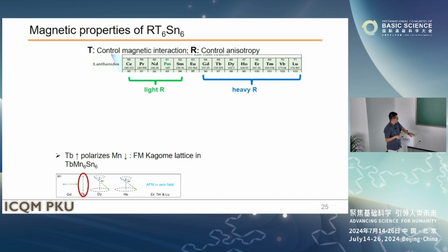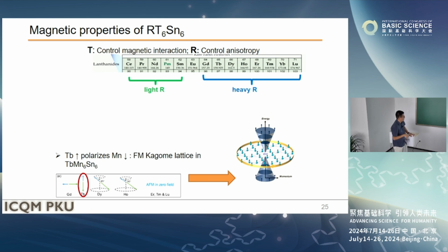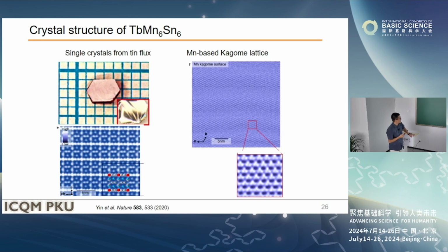And because the rare earth moment is highly localized and has strong anisotropy, depending on the crystal electric field effect, you can expect many different anisotropies for these compounds, and this anisotropy is very strong. But fortunately, we found one particular compound, terbium. Due to the crystal electric field effect, the terbium moment points out of plane. That polarizes the manganese kagome lattice out of plane as well, and this is a ferromagnetic state. And that gives you a very interesting model where we can form a Chern gap kagome magnet in experiment.